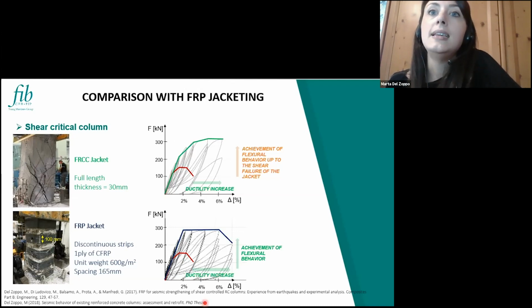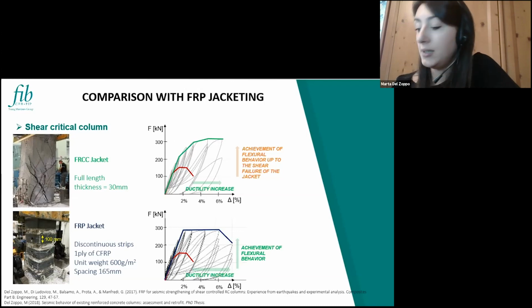And then after that, of course, the FRP, thanks to the longer fibers, so we have these continuous long fibers in the transverse direction, allows a very gentle softening behavior, while in the case of the FRCC, up to a certain level of deformation, we still achieve the failure of the jacket, and the opening of the jacket, and so a sudden loss of lateral capacity. But still, we can say that comparing the two systems, the FRCC seems to have a high potential and to be a valid alternative with respect to FRP systems, also providing additional benefits such as the increase in durability, fire resistance, and also resistance to impact loading.